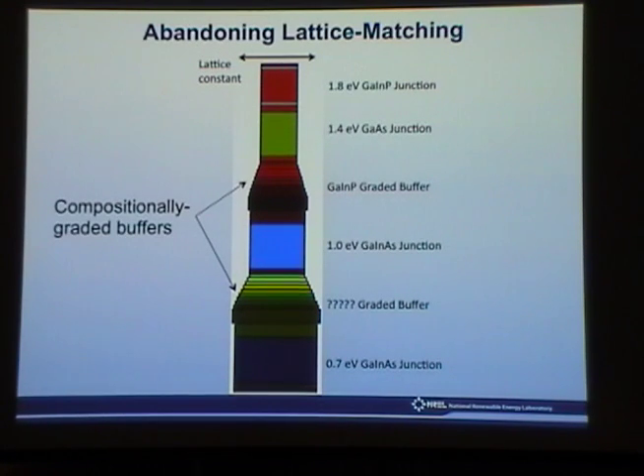If you have traps, if you have deep level traps, let's say you have oxygen incorporation, it forms a deep level trap. But if you have a high number of dislocations, then on top of whatever else already existed in the material, you've now increased the cross-section for non-radiative recombination. So you make your material worse. So I agree that you can get recombination even without the dislocations, but you're going to get more. And when you do that, you lower your VOC.